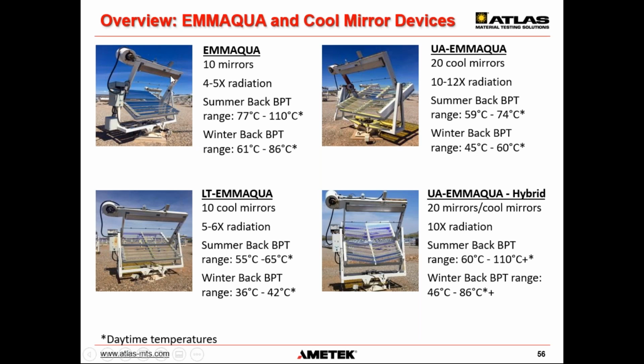So it's kind of an overview of this. We have our traditional EMA or EMMAQUA. We use these 10 mirrors. We can then use the cool mirrors in that same configuration to bring the temperatures down quite a bit. We can then go further to use this UA EMMAQUA, where we use 20 of these cool mirrors. And the latest technology that we have now, realizing that sometimes the temperatures aren't quite high enough using all cool mirrors, is this hybrid approach, where we use a total of 20 mirrors, but some of them are the traditional mirrors that will reflect back all of the visible and infrared radiant energy, and then some of the cool mirrors that are only reflecting the UV and visible parts of the spectrum. And in doing these, we can control the temperature even a little bit better with this hybrid approach.